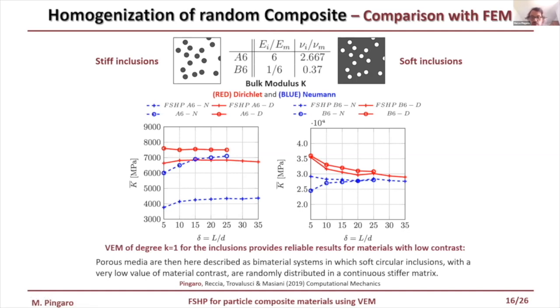The two graphs show the homogenized bulk modulus versus the normalized window dimension. In red and blue, the results are obtained for Dirichlet and Neumann boundary conditions, respectively. The circle marker is adopted for the old procedure and the cross marker for the new procedure. What can you see in this graph? In the case of soft inclusions, the solution obtained with the FSHP procedure is in very good agreement with the previous one, but in the case of stiff inclusions, the results of the new procedure don't match the results of the old procedure.